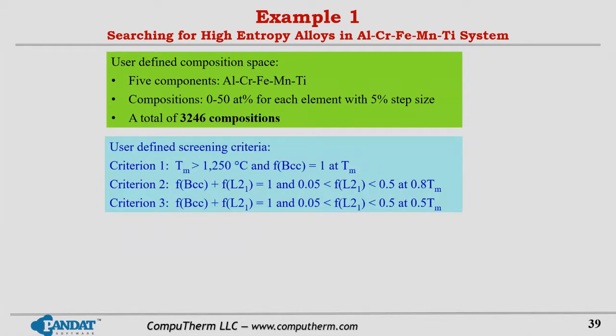After that, the user defines the screening criteria. For example, criterion number one is that the melting temperature should be higher than 1250, and the first solidified phase should be BCC phase, which is basically the matrix phase.